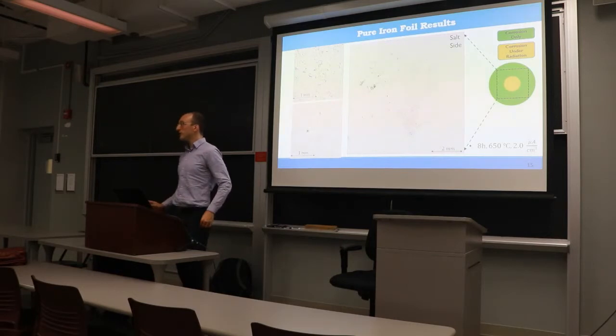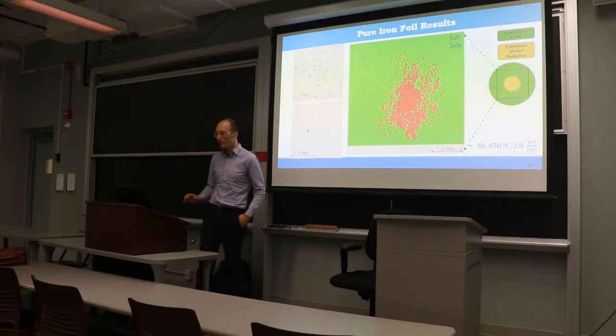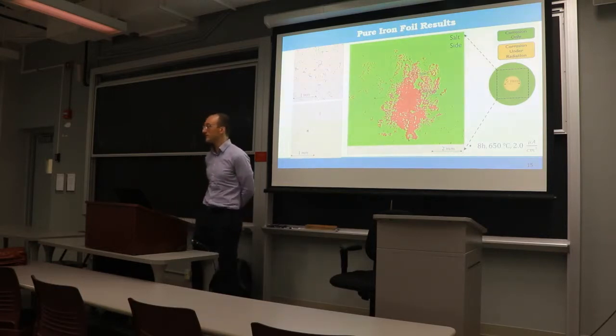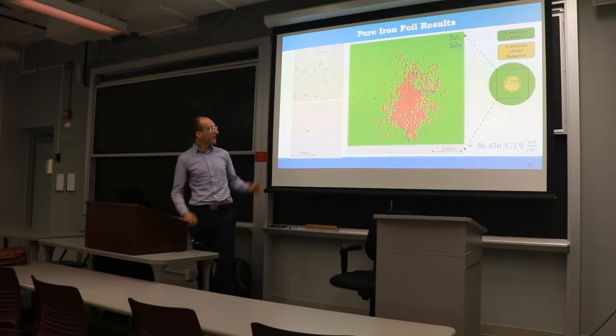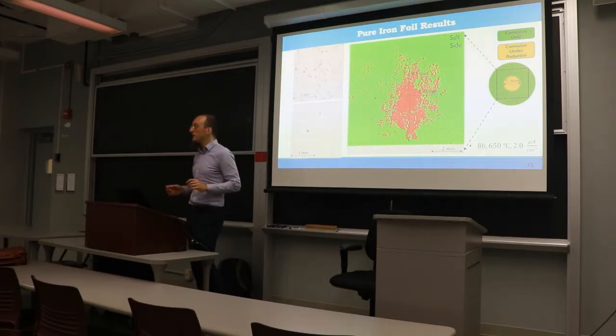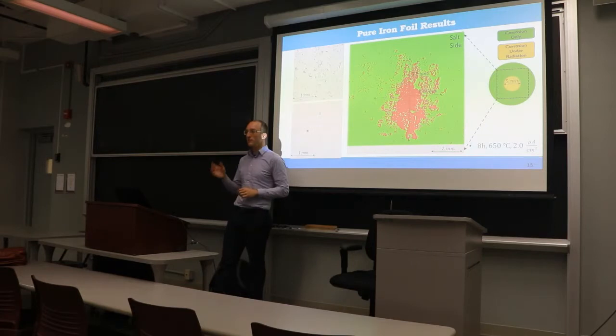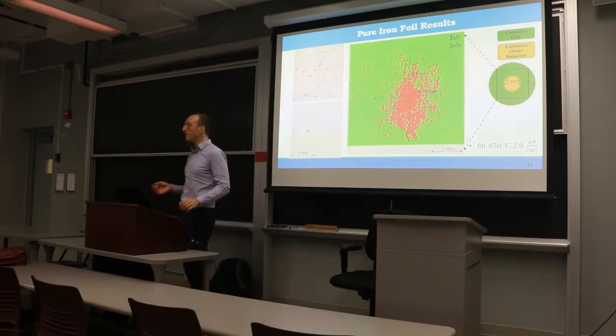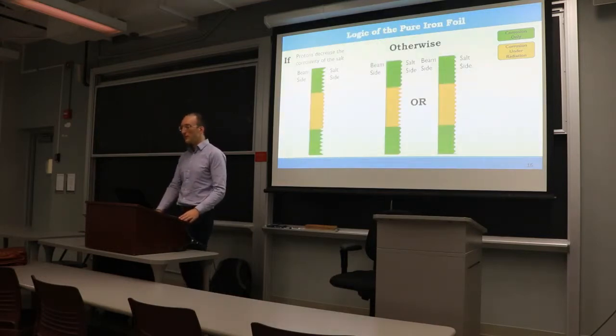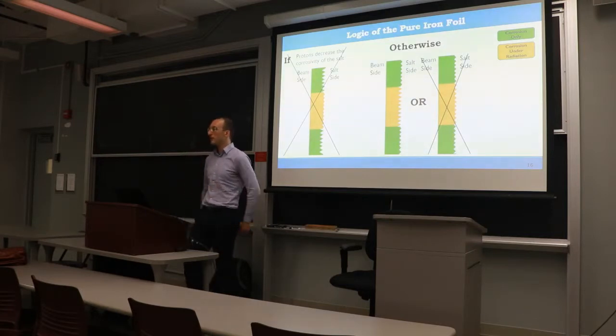We also trained a machine learning algorithm to identify where intergranular corrosion was worst, and we're able to image the corrosion spot and verify that it was indeed the same dimensions as the beam, which is pretty cool. And the fact that it's fuzzy is actually expected too, because if this is a chemical effect of the protons making the salt more corrosive, then it shouldn't be localized to a perfect circle. Chemicals spread and there's convection currents in the cell, and it should be messy. Not like we saw with the radiation accelerated corrosion. And so we're able to confirm our hypothesis and disprove the competing ones, which were brought up by a lot of folks that know this stuff.